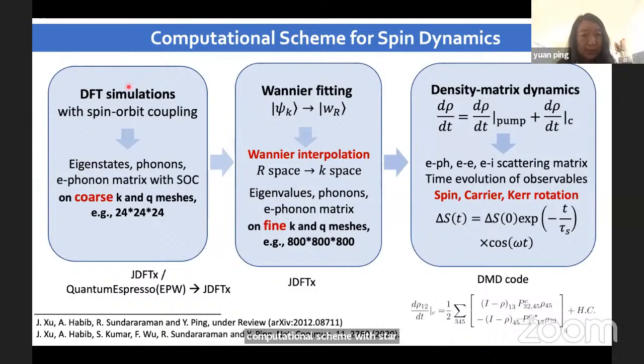We start with the DFT simulation with the spin-orbit coupling with the coarse mesh, where you can get the eigenstates, the phonons, and electron-phonon matrix elements. And the electron-phonon matrix elements you can get from Quantum ESPRESSO, or use another code from our collaborator, JDFTx. And then you do the Wannier fitting, and you can extrapolate to a very fine mesh, which is necessary for our implementation to converge the k and q points. At the end, we do the density matrix dynamics, where the scattering matrix needs to be computed. Then you do the time evolution of rho, and then you can look at your observables.